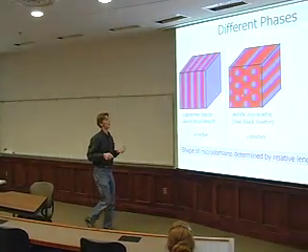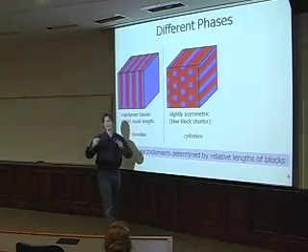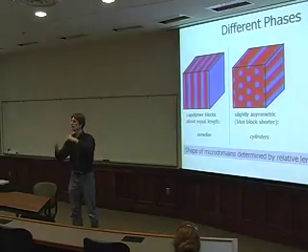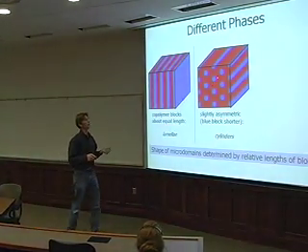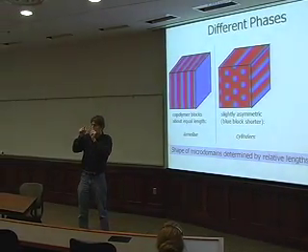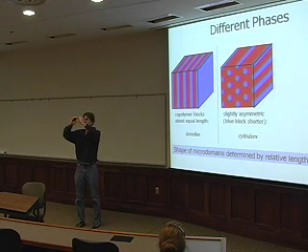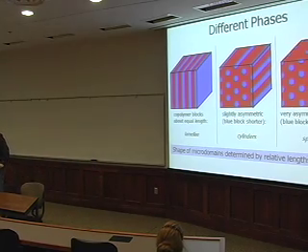And again, the structure of this is that each of these blue cylinders in here is actually made up of the blue ends of the molecules, all blue side in on this cylinder. So that cylinder is actually made up of the conglomeration of lots and lots of different molecules. And you can play this game a little more and say, what happens if I magically go in and make the blue ends of these molecules even shorter? Well, for starters, the cylinders would start to get smaller and smaller, and then at some point they'd break up again into little spheres.